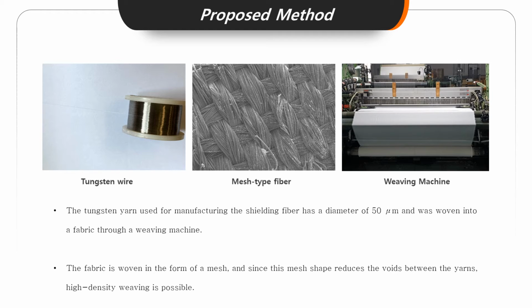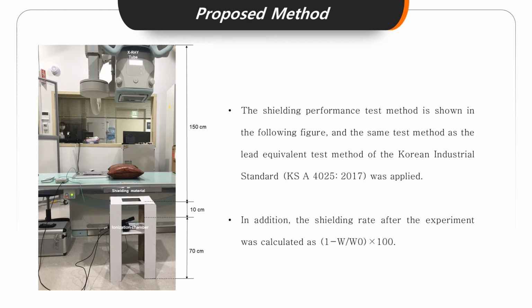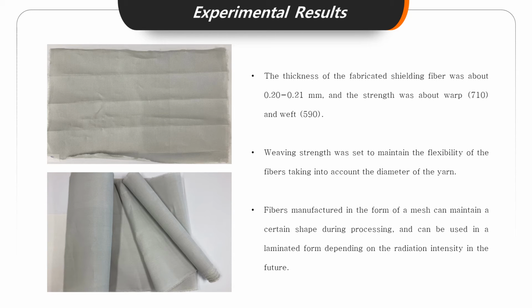The shielding performance test was conducted as shown in the figure. In order to test the shielding performance of tungsten fibers, the Korean industry standard lead equivalent test method was applied. In addition, the tube voltage was set sequentially from low energy to high energy used in medical institutions. It was measured with an X-ray generator and a dose detector, and the shielding efficiency was calculated using the following equation. The thickness of the fabricated shielding fiber was about 0.20 mm.